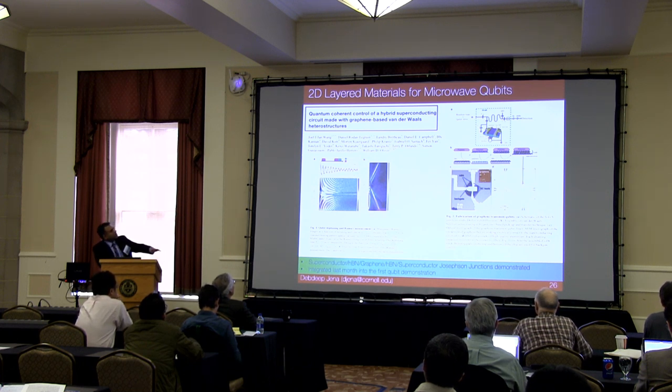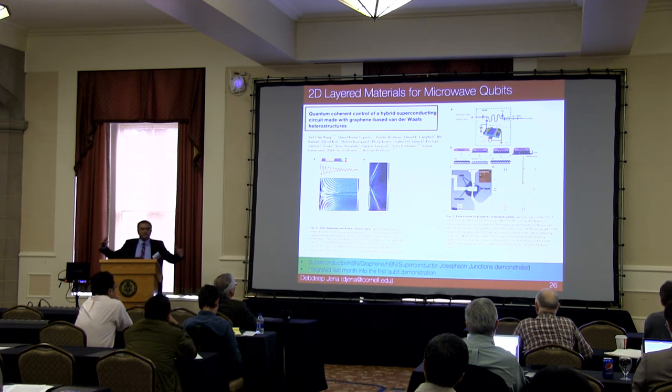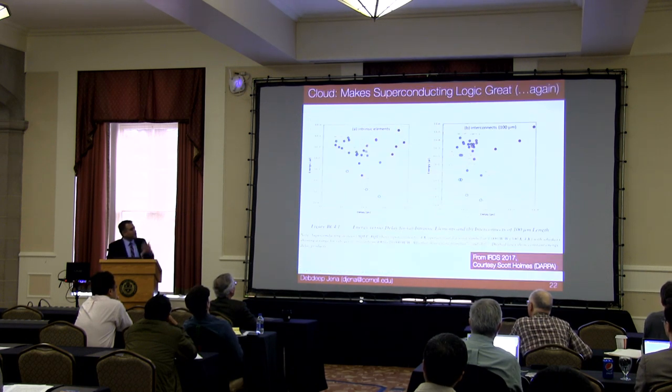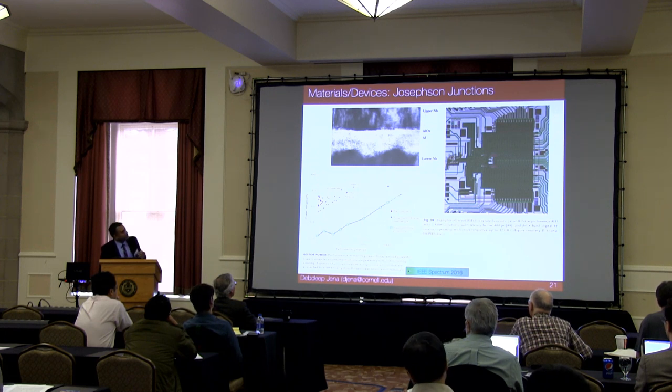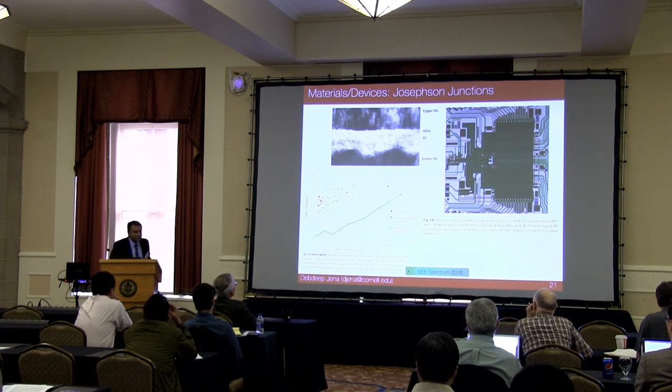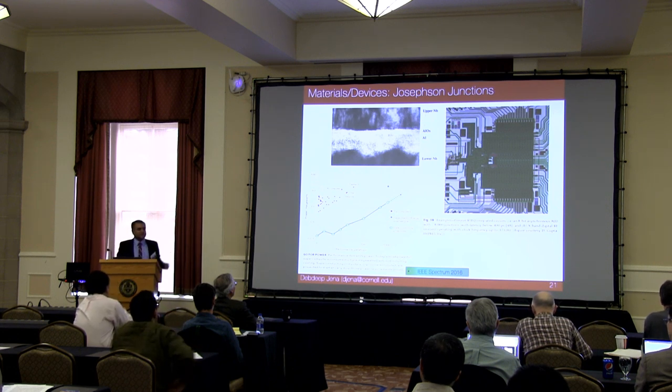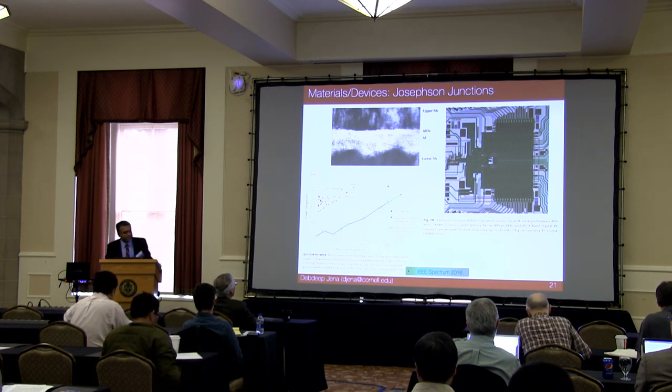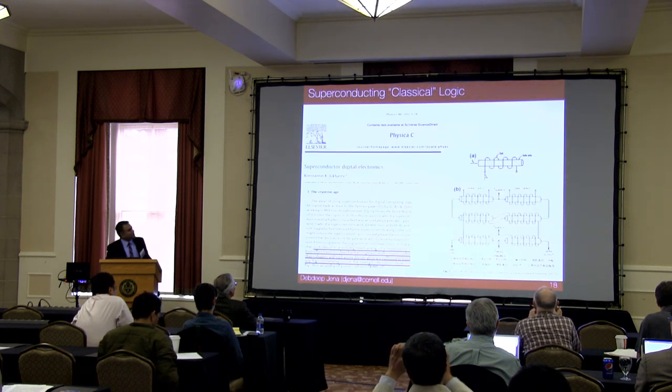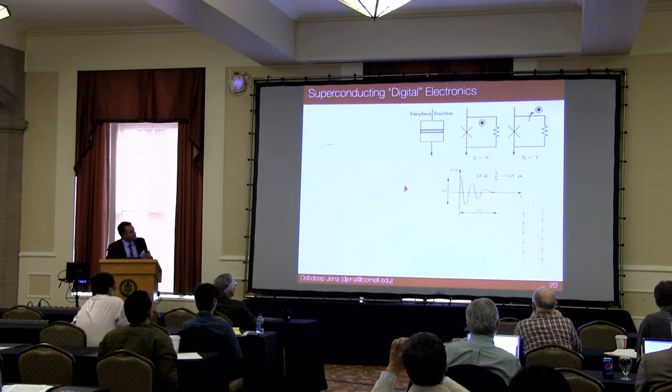When you look at these transistors, they can switch at about half a terahertz, 400 to 500 gigahertz. It's no problem. So even at 100 gigahertz, they can generate milliwatts of power today. And that is really driving the new communication technologies forward. But this is made of gallium nitride. And interestingly, if you look into the periodic table, here you have niobium. And niobium nitride is one of the most interesting superconductors. And if you look carefully, it turns out that the crystal structure of gallium nitride is very well matched to that of niobium nitride. If you look at the lattice constant of niobium nitride, it falls very close to gallium nitride.